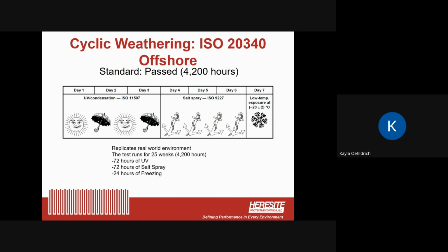It's a 25-week test where it cycles 72 hours of UV exposure, 72 hours of salt spray, and 24 hours of freezing. All of our coatings pass this ISO offshore cyclical weathering test. It's very important for us. We test our competition, and there's a number of them that do not pass this test. They may say they have high salt spray hours, but we don't think that they perform as well as our products using the offshore cyclical weathering test.